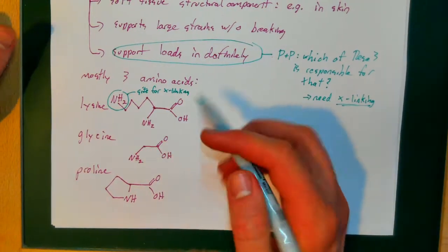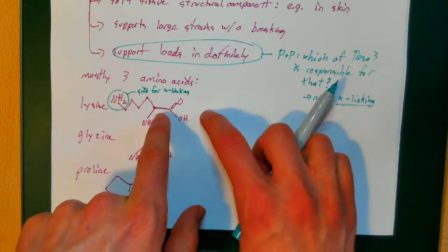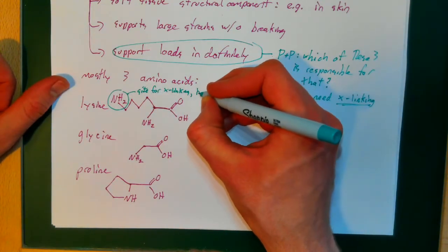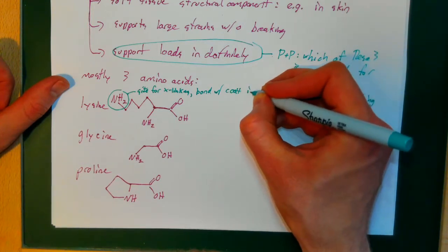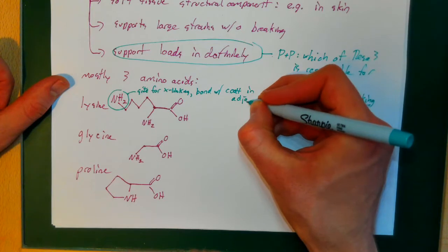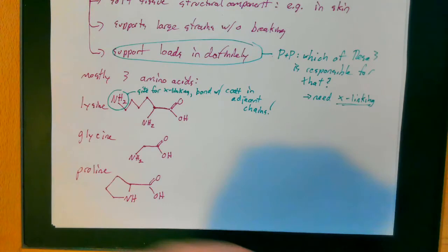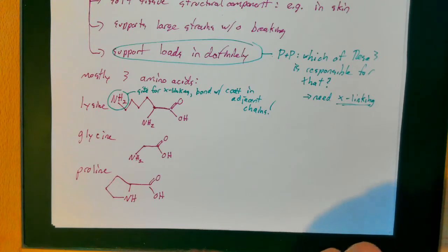And what does that mean? Basically, the amine group and carboxylic acid can form a chain, but there are periodic NH2s sticking out of those chains, and those NH2s can bind with carboxylic acids of adjacent chains. So this site can be for cross-linking, bonding with carboxylic acid in adjacent chains. Isn't that awesome? It has built-in sites where we can cross-link to other chains.